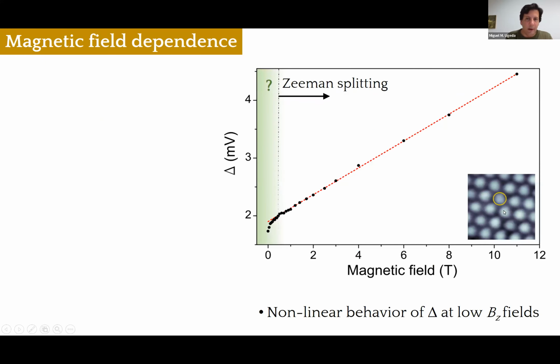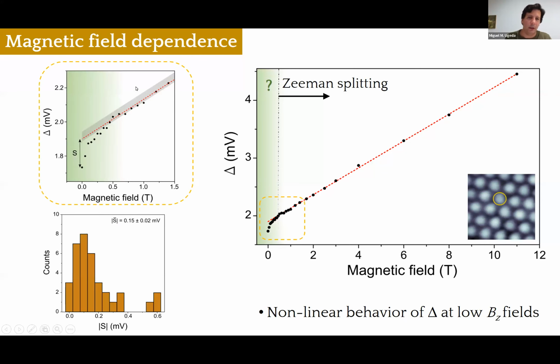So there is something else that we have learned from the magnetic field dependence. Here I'm showing you a plot of delta. Delta, let me remind you, is the separation between the two peaks as a function of the magnetic field. Here we can distinguish two different regimes. The first regime is for magnetic fields larger than 0.5 Tesla or so, where we see a strictly linear dependence of these two peaks, which we of course ascribe to the Zeeman splitting. But interestingly, for magnetic fields below 0.5 Tesla, the system is highly non-linear. Here I show you a zoom of this particular set of data, where you can see that below 0.5 Tesla, the system leaves the linear dependence.